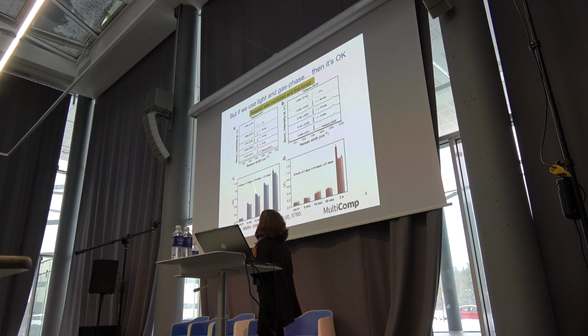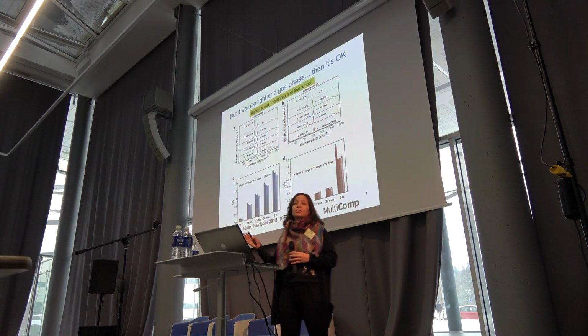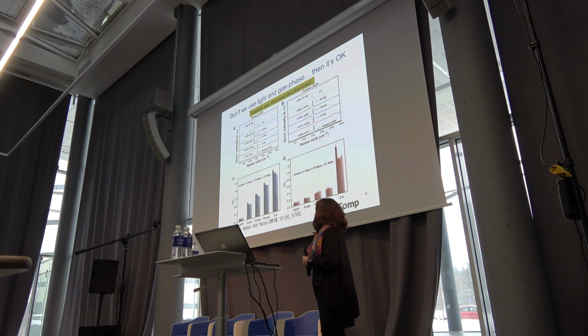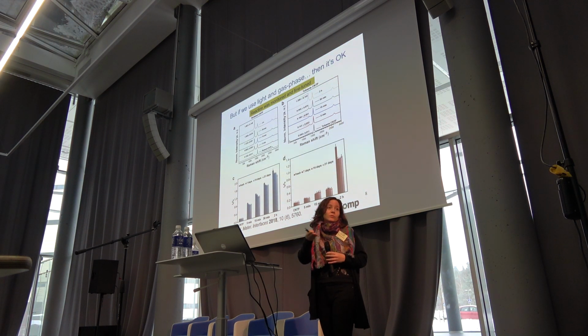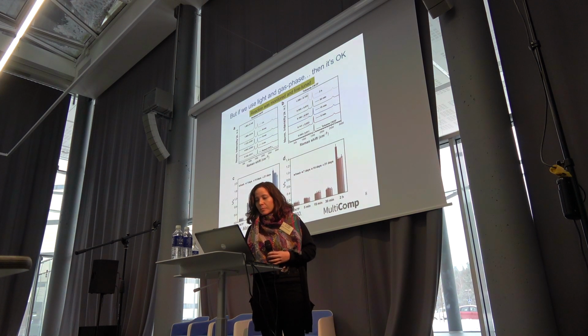And this means that these ones are more reactive, and these ones are a little bit less reactive, but you can still oxidize them eventually. And so you can fine-tune the level of oxidation depending simply on the reaction time, so basically the time that your substrate stays in contact with the high energy UV. And in each case, the functionalization was monitored for over 3 weeks, and it was pretty stable.